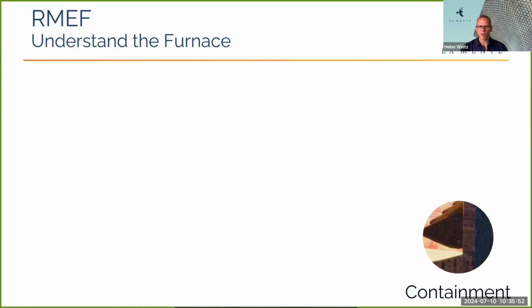Okay. Then the last component of understanding the furnace is containment. Now there are three containment strategies that at least we are aware of. The first one is that of sidewall feed heaps. By feeding large amounts of material close to the sidewall, it serves as a heat sink, and that helps to limit contact between very high temperature slag or matte and your refractory material.